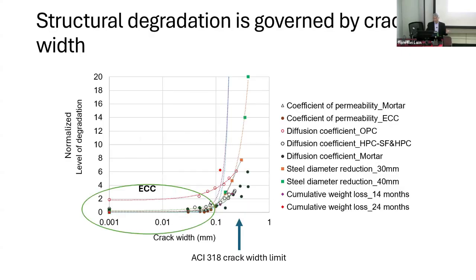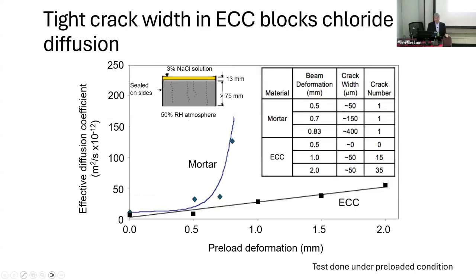Now, that's permeability, but you can do the same kind of study with regard to chloride penetration. And we did this, again, deliberately loading the specimen under bending before exposing it to a high concentrated chloride solution. And you see that the effective diffusion coefficient responds to preload deformation. For the mortar, it goes up very, very fast. With the increase in crack width as you bend the specimen, the chloride diffusion rate goes up very high. In ECC, it also goes up, but in a more linear fashion.